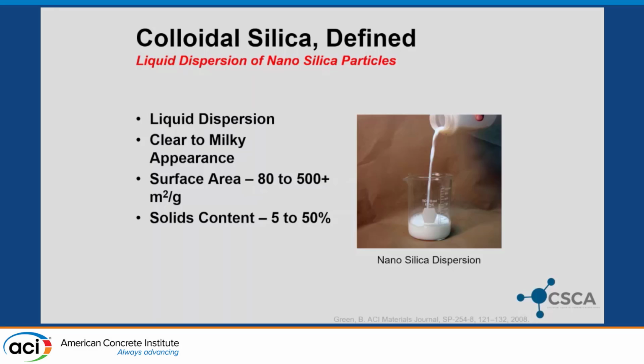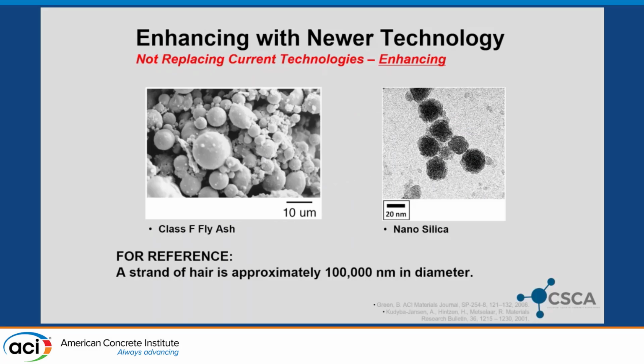I say colloidal silica because there is nanosilica. You can buy dried nanosilica. My preference is using it in a liquid dispersion, clear to milky, with a specific surface area anywhere between 80 and 500 square meters per gram. And the solids content can go anywhere from 5 to 50%.